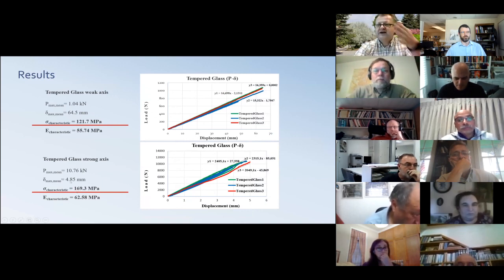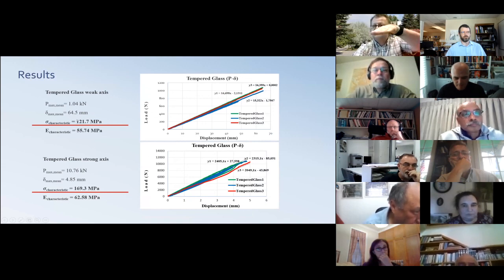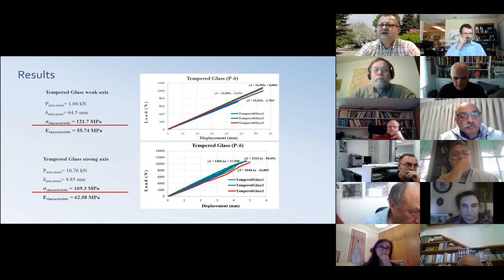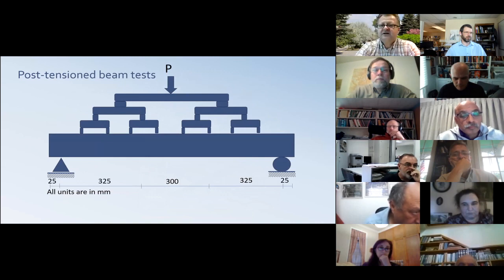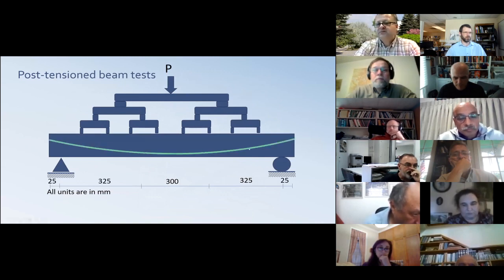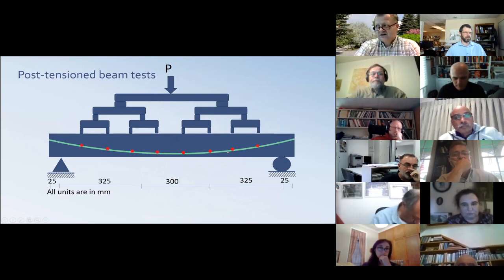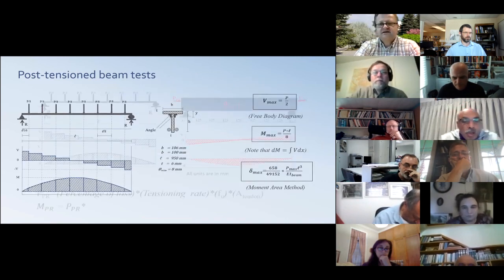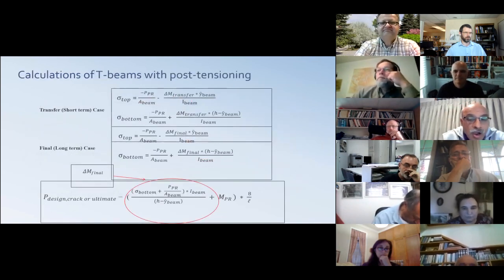This is the strong axis when you put the glass like this, and this is the weak axis when you put glass like this and apply the bending. So they behave differently. After knowing this, we applied this distributed load and the post-tensioning. So we did this with plain glass and tempered glass, and we got the results.